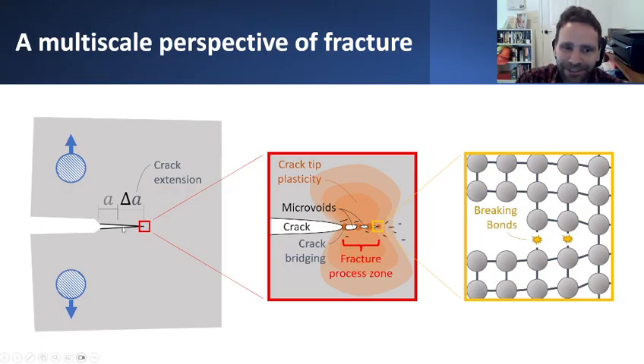At a macroscopic view, it certainly looks like there's a crack there or there isn't, and that's the whole story. At the micro scale, it's a much more complicated picture, and really it is a process. It has to go through a whole sequence of different fine scale mechanisms to ultimately lead to visible crack extension at the macro scale. And if you look even further down, to look at any one of these micro cracks or maybe at the edge of a growing micro void, what you'll find is that the true atomistic scale perspective of fracture really corresponds to atomistic debonding. So breaking of the bonds between atoms in the original lattice configuration of the material.